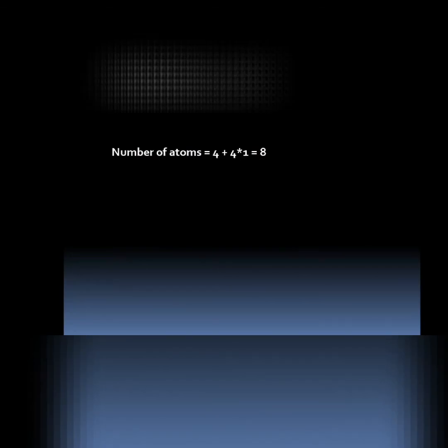Now packing fraction is equal to 8 into 4/3 πr³ into 100 divided by a³. 8 is the number of atoms, and 8 into 4/3 πr³ is the volume occupied by the atoms in the unit cell, and the volume of the unit cell is a³, and by multiplying by 100 we can get the packing fraction of the diamond crystal system.